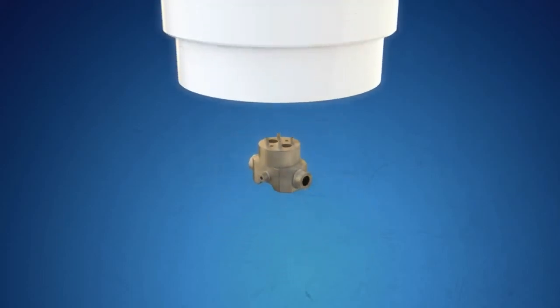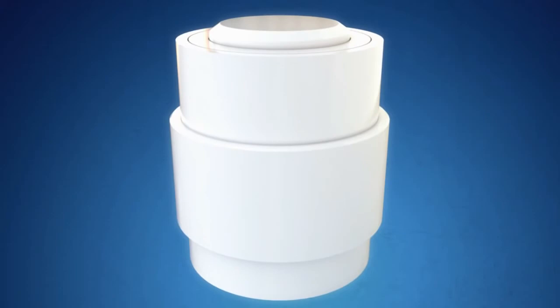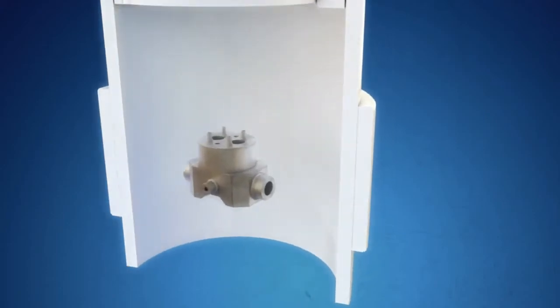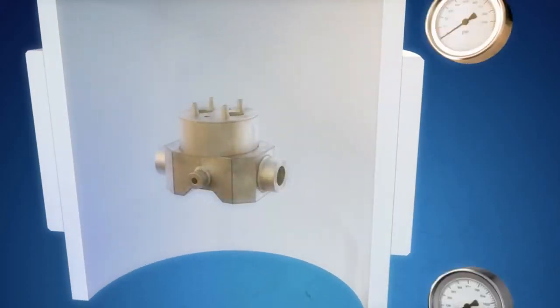The filled capsule is evacuated and inserted into a cylindrical hot isostatic press. This is where the hot isostatic pressing process begins. To obtain 100% densification, the capsule is exposed to high isostatic pressure using argon gas and applying high temperature. The volumetric shrinkage during the HIP process is approximately 30%.